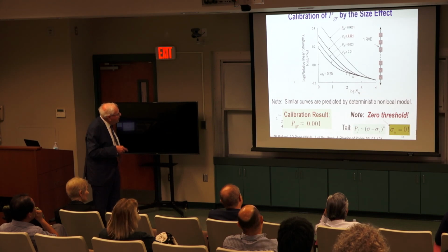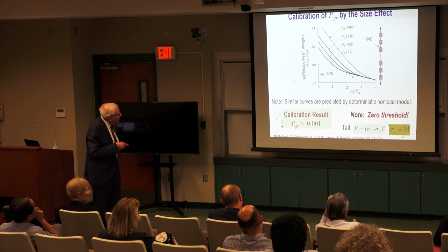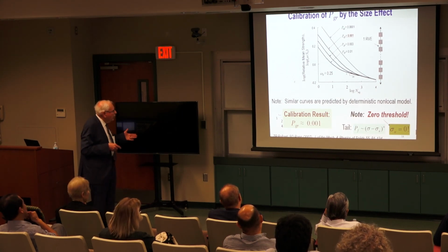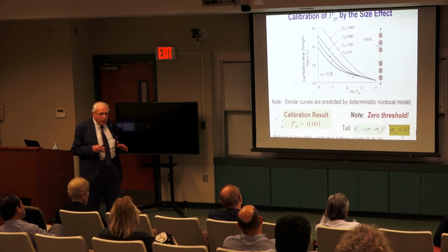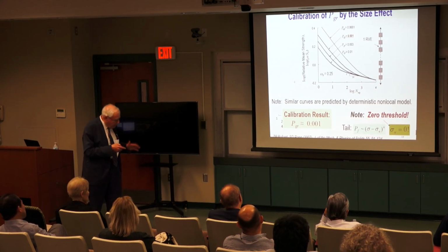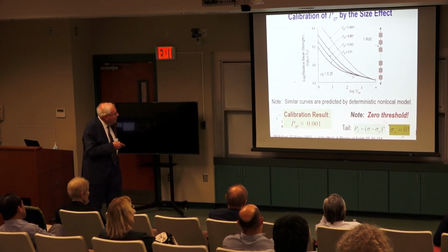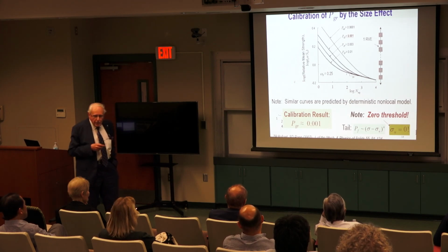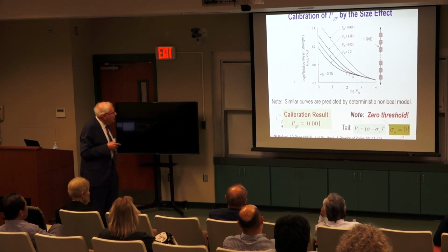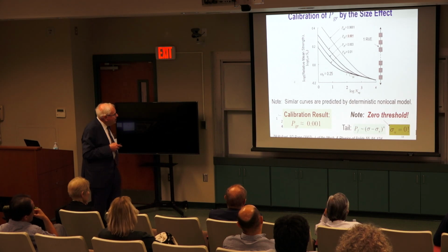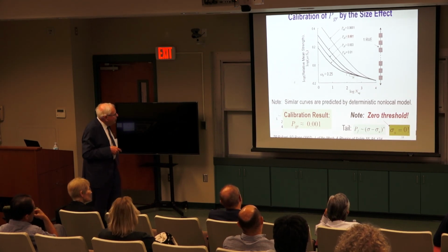And if it's the size effect, it will shift at 1,000s, 10,000 here, 1,000s, 100s, and see what the experiment shows. Now, interesting that for all quasi-brittle similitudes, the transition is about 1,000s. So that's empirical. We could not predict it, but it's empirical. And it's easily tested, and from this actually you can infer back what is the distribution.